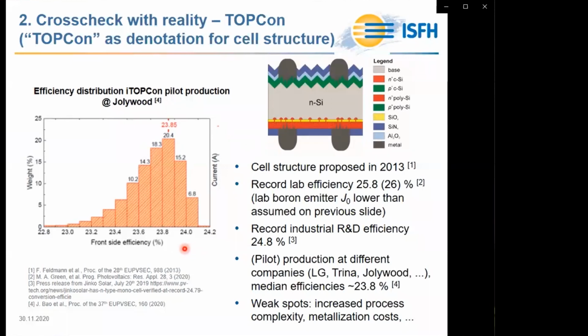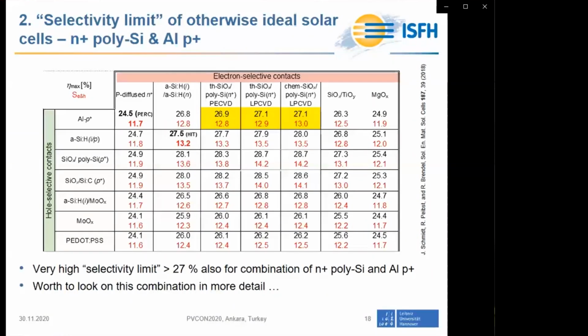In particular, the process complexity is increased as compared to the PERC cell, and also metallization costs are increased because the rear side is metallized by silver rather than by aluminum. Last but not least, let's consider the combination of an electron-collecting polysilicon on oxide junction with a hole-collecting aluminum P+ junction formed by aluminum alloying. This combination has a surprisingly high combined selectivity of up to 13 and a corresponding selectivity limit exceeding 27%. And therefore we think this combination is quite interesting and worth to look at in more detail.